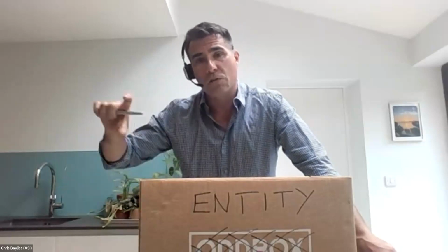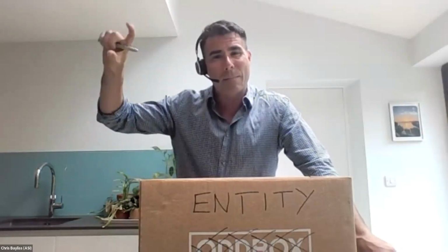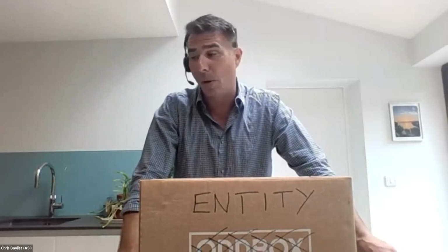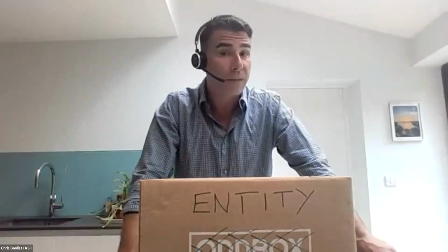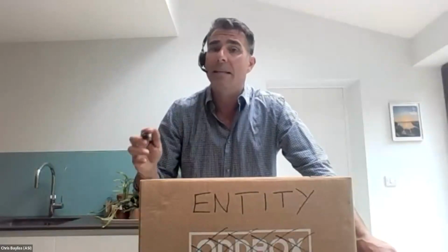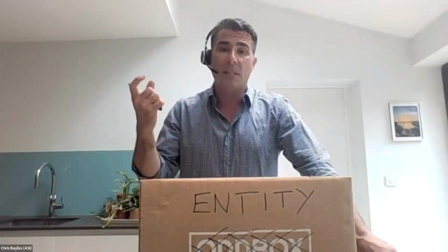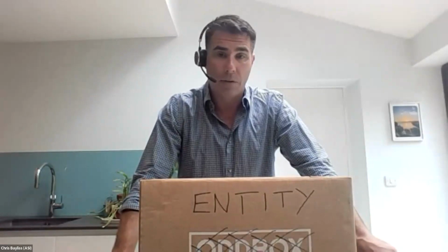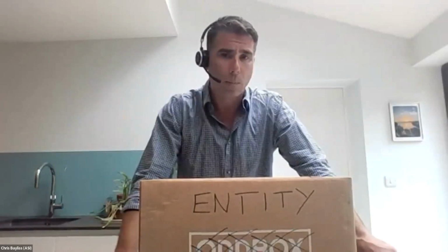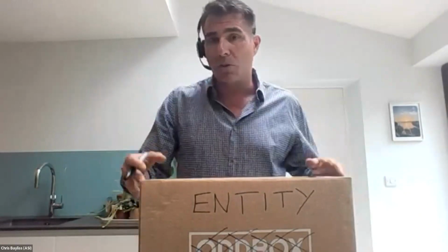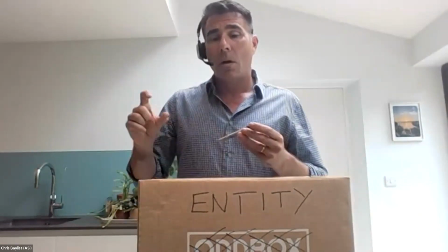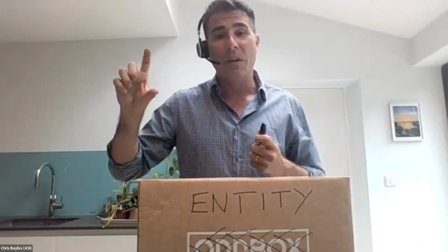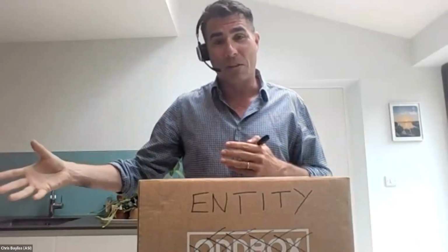But that also means that the scrap that's generated has the same percentage tied to it. So of the 20 tons of scrap generated by that COC certified entity, only 50% of that scrap is eligible. That needs to be recorded in the material accounting system, which is ultimately the data that is sent to us every year under 1.7 for those of you who report 1.7 data. That's why you'll see that we've started to ask for output of total scrap as well as output of eligible scrap from COC certified entities.